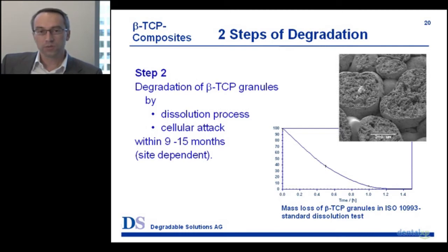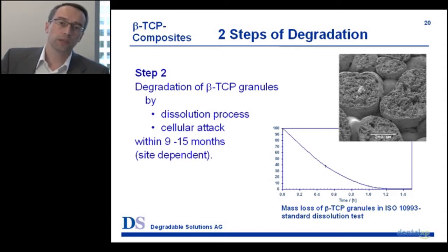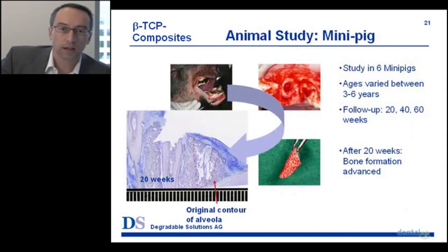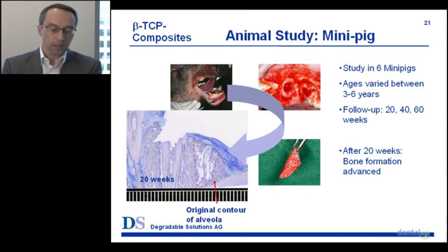After 40 weeks you do still see some residual material in the core of the implantation site, and after 60 weeks you cannot see that anymore. After 60 weeks we went more into details at the site where we placed the graft, and we even went to a transmission electron microscopy analysis, and we found after 60 weeks that there were still some small TCP particles present, but they were all outside the extracellular matrix and grabbed by giant cells.